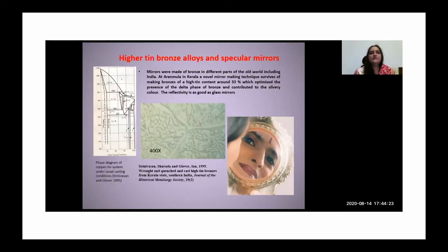So now I come to the making of the mirrors. And here, what was happening is actually this phase, which was only forming in the grain boundaries in the first piece that I showed you, that network. So for the making of these specular mirrors, what was done was that they were actually aiming for this delta phase composition, because this delta phase, though it is very embrittling, also gives certain properties, because it is a very specular material. So it gives a very good mirror finish and so on.